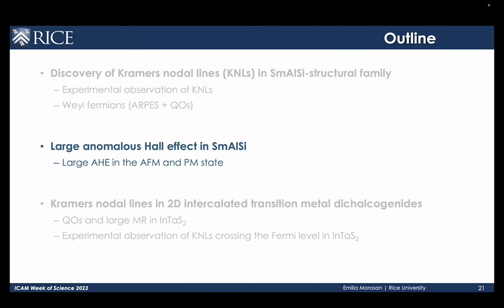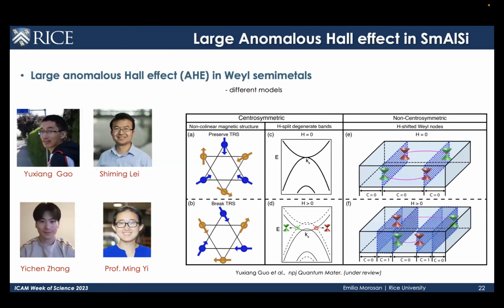I'll just move on to briefly tell you about the large anomalous Hall effect that we discovered in samarium aluminum silicon. We found this both in the antiferromagnetic and in the paramagnetic state. And the punchline here is that we are proposing a new model to explain the large anomalous Hall in this particular compound and in this class of compounds. And the new model is based on field-shifted Weyl nodes in this non-centrosymmetric crystal structure.